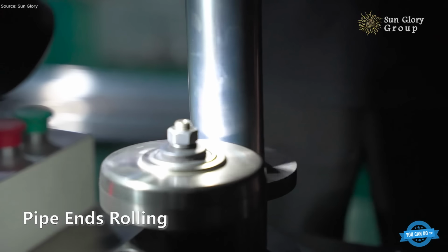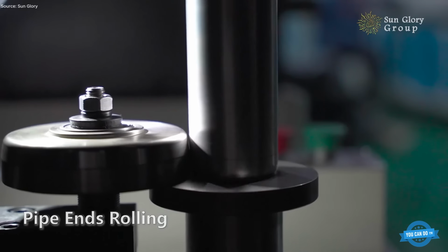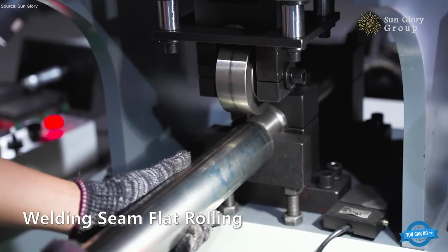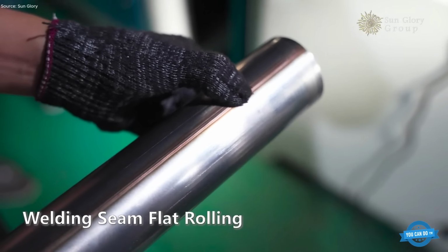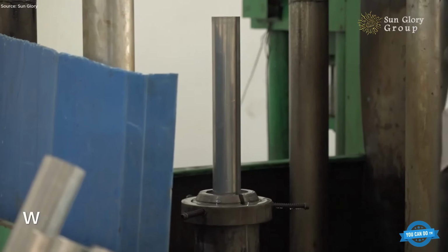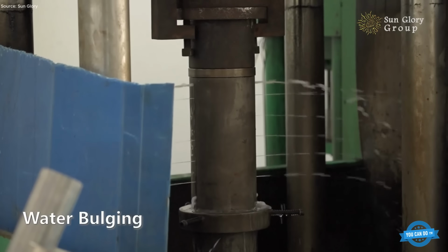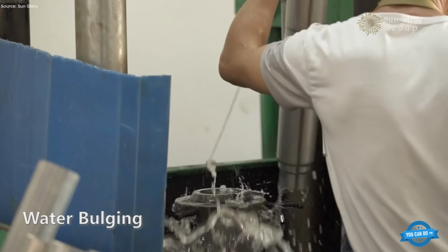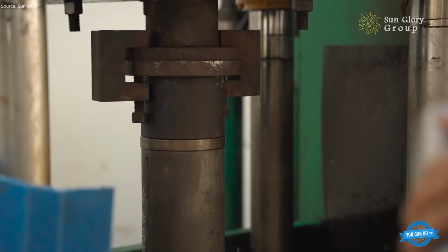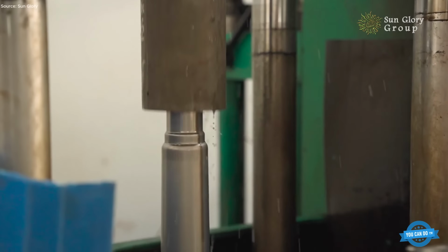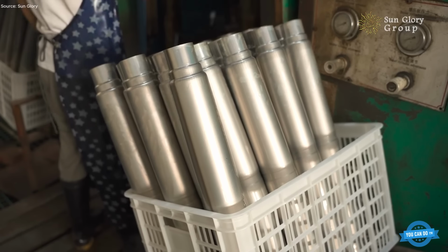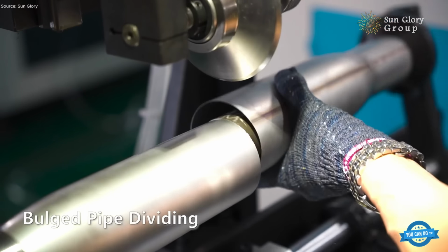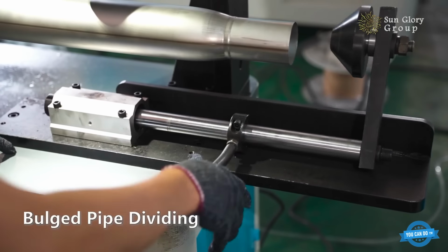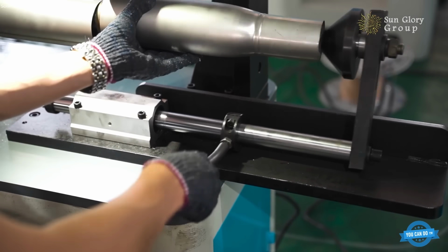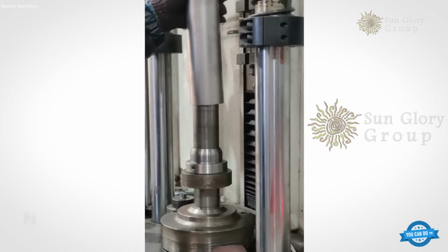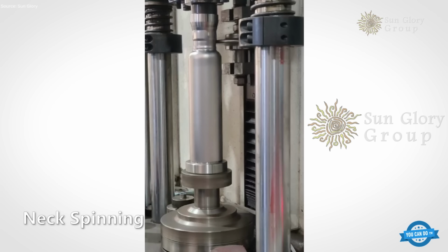The manufacturing of a stainless steel vacuum thermos flask is a complex industrial process that combines precision forming, welding, surface treatment, and vacuum technology. After this preparation, the pipe undergoes water bulging, a forming process in which high-pressure water expands the metal inside a mold to create the flask's characteristic curved shape. Once formed, the bulged pipe dividing step separates the material into individual flask bodies. The upper section then goes through neck spinning, where rotating tools shape the narrow mouth of the bottle. This is followed by rim neck cutting to refine the opening.